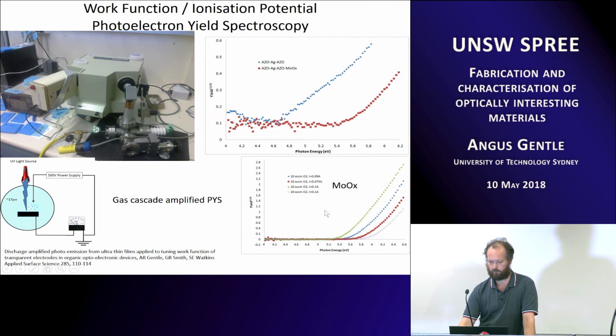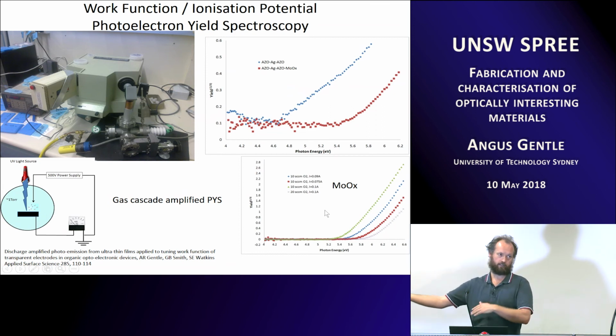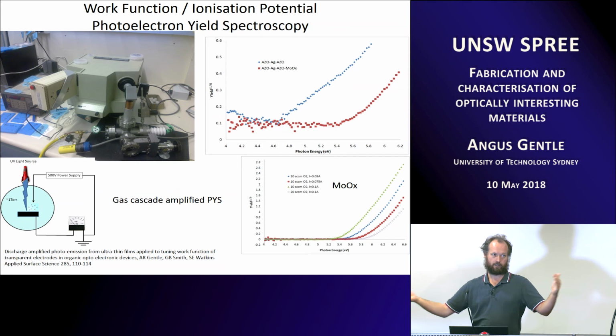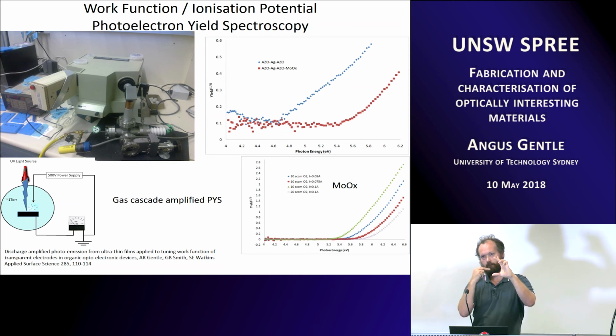So in this case with moly oxide, we went all the way from MoO3 through to MoO2. And so basically you end up having a defect state which comes in about 1.5 eV above the valence band, which then gives you the right work function.